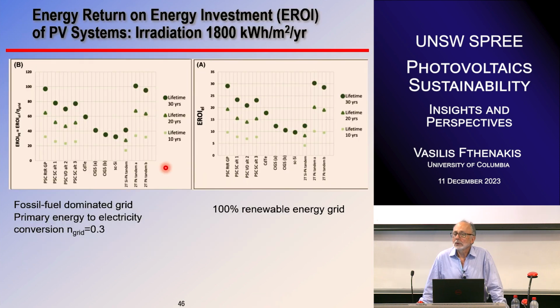Now, all of the comparison so far assumes perhaps the same longevity, the same life expectancy. But as you know, perovskites are not really tested for very long lives yet. I mean, we're talking about less than a year of studies in the lab. So here we ran energy payback or energy return on energy investment for different lives, 10, 20, and 30 years, and compare the 4 thin film perovskite and the 3 tandem with the conventional ones. And what we see for different grids: the current fossil fuel dominated grid and also a grid that will be mostly renewable energy, where you replace electricity with electricity. For a fossil fuel dominated grid, you replace primary energy from electricity, so you have higher benefits there because, again, electricity is a higher quality of energy.